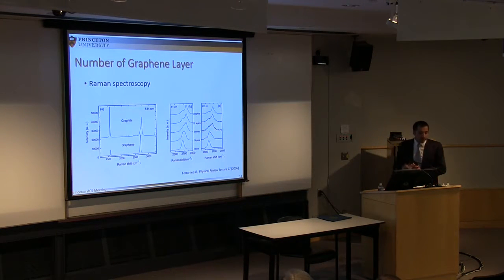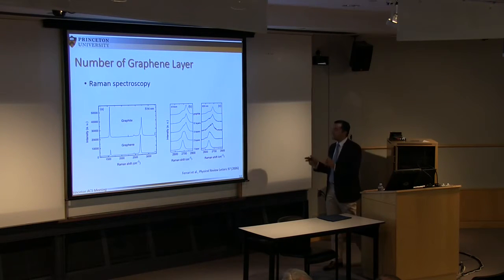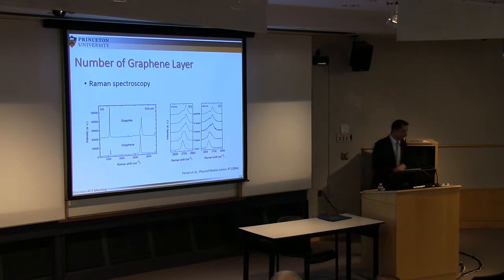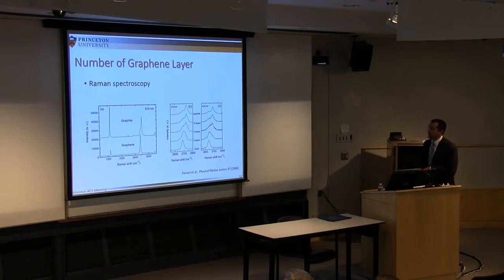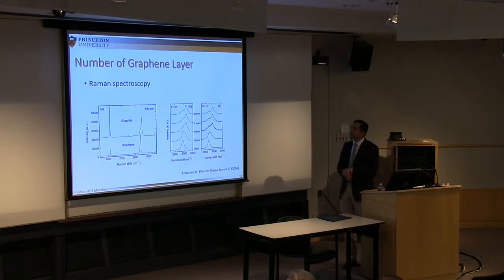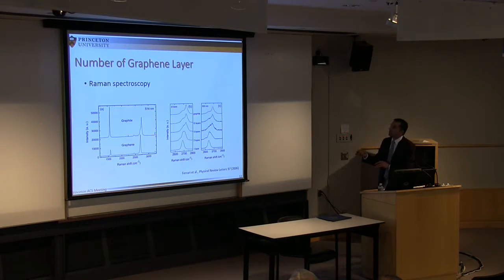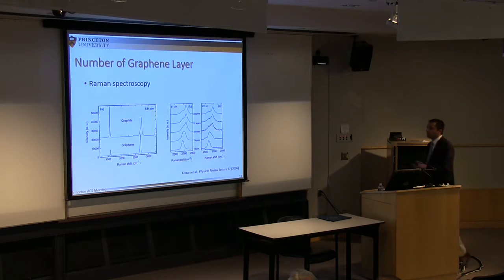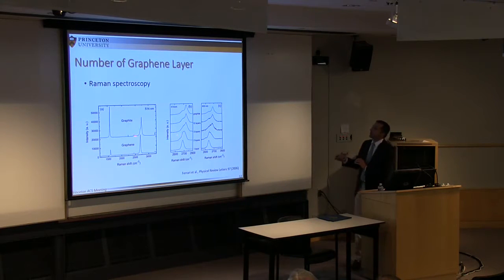So again, keeping in mind the importance of justifying the presence of a single layer, another way that was developed, again by the Manchester group, was the use of Raman spectroscopy. So this is the spectrum for graphite. It has two characteristic peaks, here the G band and here the 2D band, which is clearly a signature of its electronic structure. And graphene also has two nice peaks at the same location.